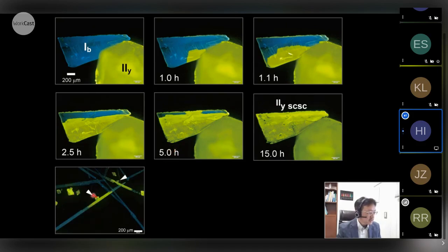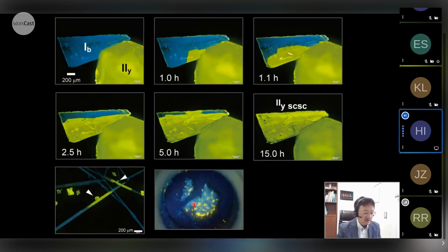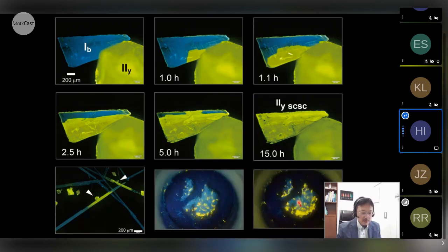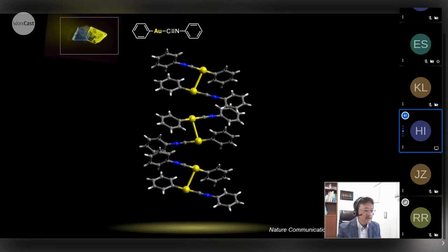Similar contact-induced color change was observed like this. And if you mix the yellow and blue crystals, you can observe development of the yellow part after 2 hours. The other interesting thing is that this crystal change proceeded through single crystal to single crystal phase transitions. So we can analyze the structure of this part.